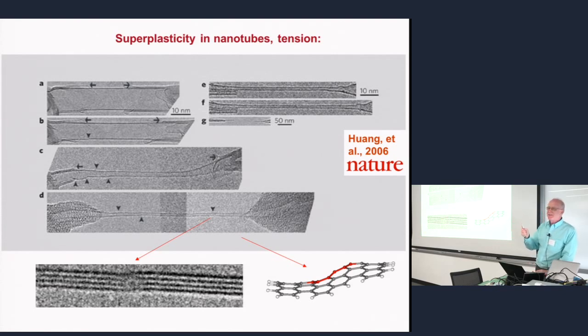They actually do see these dislocation signatures because they look like this. This is dislocation, 5-7. And they see them moving. If they move around, you don't see it go around, you just see that one thing disappears and then appears on the other side. So you basically can be sure that they go around this spiral. They just glide spirally. And this was experimental evidence of this superplastic behavior through this mechanism that I just described to you.